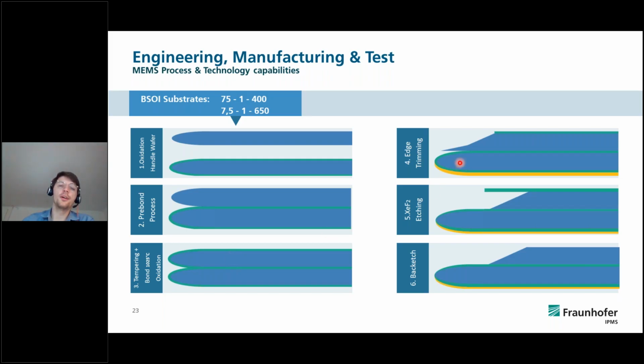Then we did the edge trimming to get rid of the edge and not have any issues with the edge of the wafers. Get rid of the silicon that lasts on the edge by xenon difluoride etching, and later on we get rid of the oxide on the top side and grind back to the target of the device wafer. So this is the basic idea that we had in mind. This was the project idea.